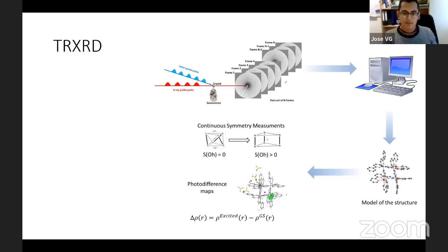of the camera. So time resolved photocrystallography is something similar to that. First, instead of using a flash, we will have a laser pulse which excites the material, so the material in the single crystal, and after that, an X-ray pulse will arrive and be used to take the image of the pattern inside of the crystal, so the reciprocal image. And after taking many images, we can process all those images in the computer to obtain the model of the structure. And after we have the model, we can actually analyze the changes of the structure.